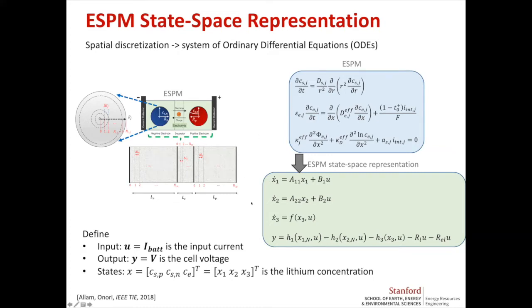And so by doing discretization in the solid particles and in the electrolyte direction, we can now translate the PDE model into an ODE model. The control input of this model is current, and the voltage is the output that we measure. So we have access to voltage sensors. The cell voltage is expressed as a function of the overpotential, the open circuit potential, the electrolyte resistance, and the battery current as well.